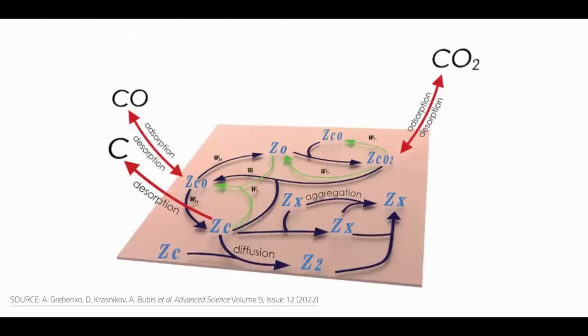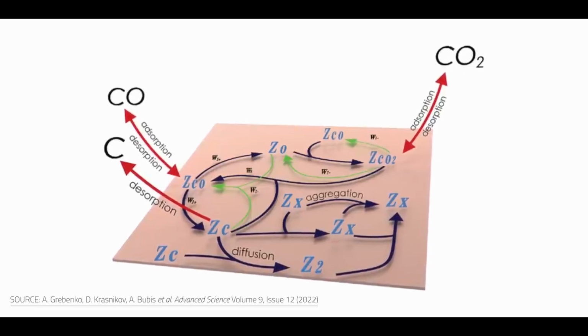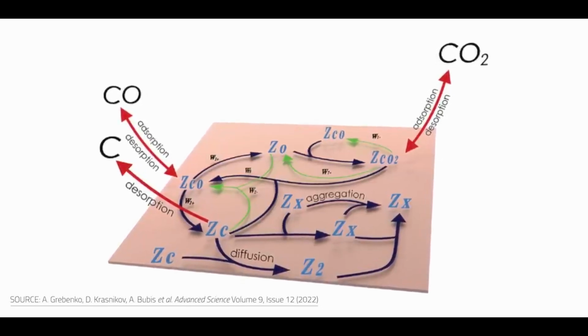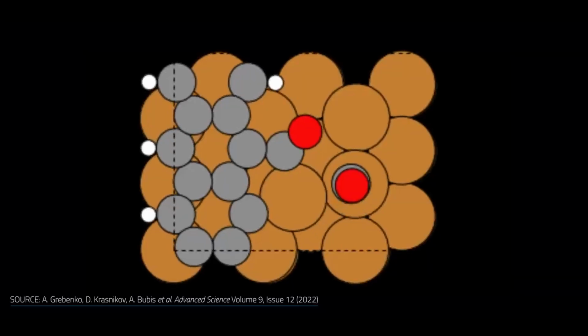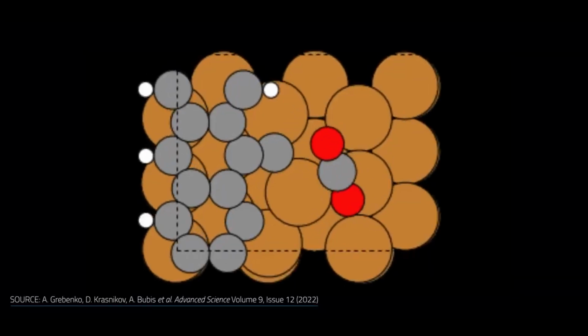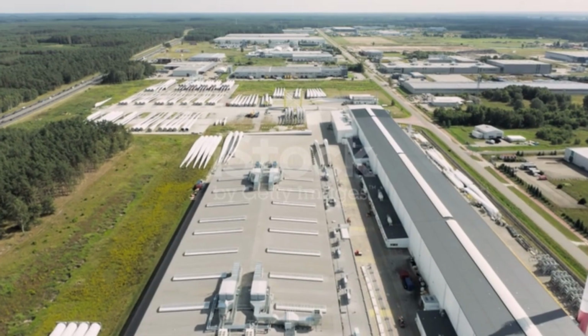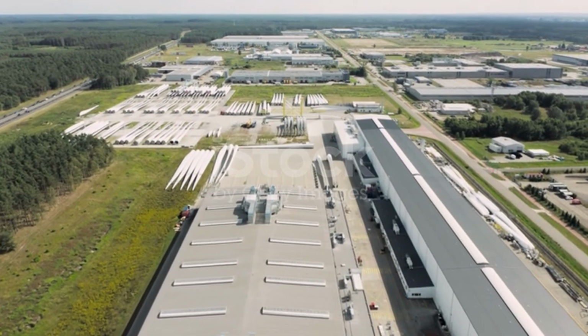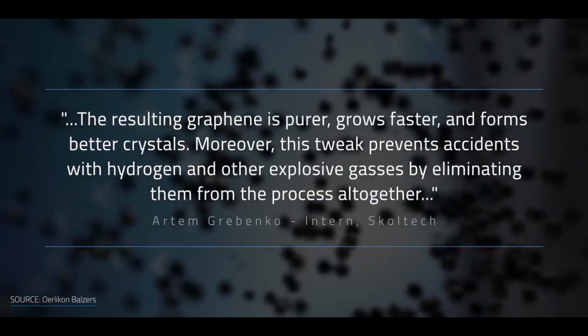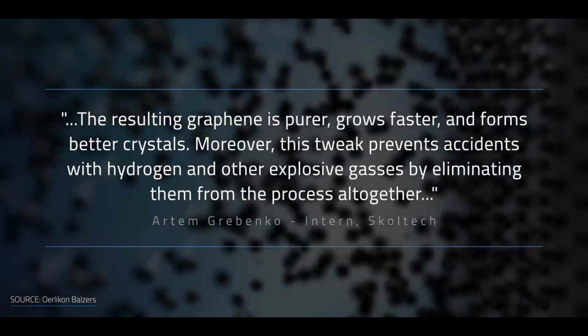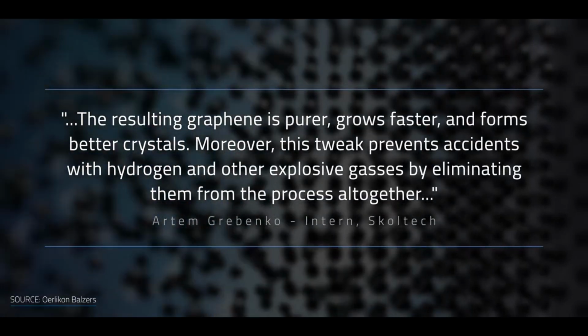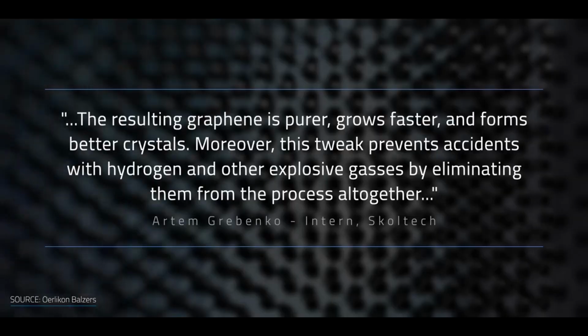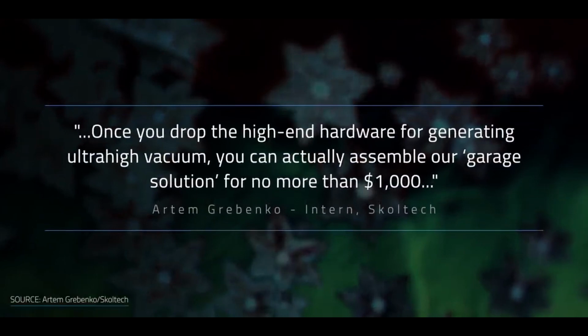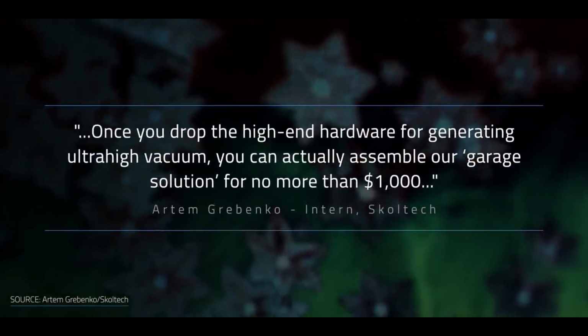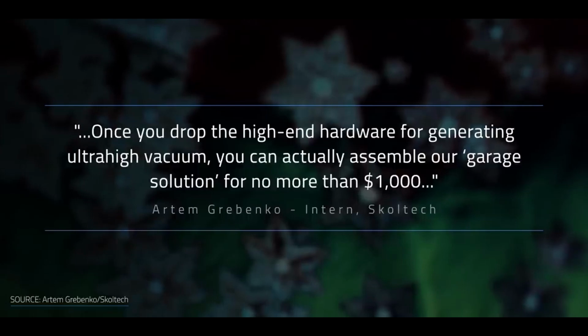When carbon monoxide molecules get close to the copper substrate at high temperatures, they tend to split into carbon and oxygen atoms. This propensity fades when the first layer of crystalline carbon is produced and separates the gas from the substrate. According to Skoltech intern Artem Grebenko, the system offers several advantages. The resulting graphene is purer, grows faster, and forms better crystals. Moreover, this tweak prevents accidents with hydrogen and other explosive gases by eliminating them from the process altogether. When it comes to costs, Grebenko pointed out, once you drop the high-end hardware for generating ultra-high vacuum, you can actually assemble our garage solution for no more than $1,000.